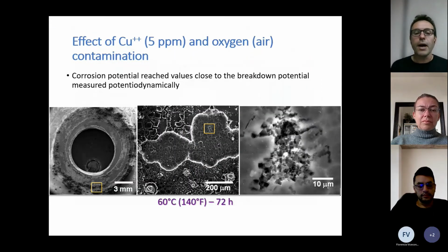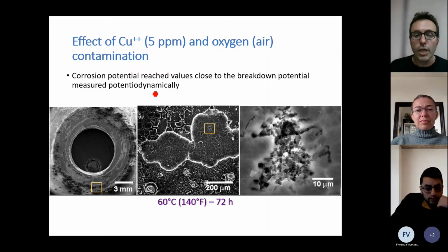So bad things happen with aluminum. I said aluminum doesn't like copper. So what we did on purpose was add some copper, just 5 ppm, and did the experiments under aerated conditions. And what we saw is that even at the open circuit potential condition, when you have copper and you have air, the open circuit potential goes all the way up to values close to the breakdown potential, measured potentiodynamically.